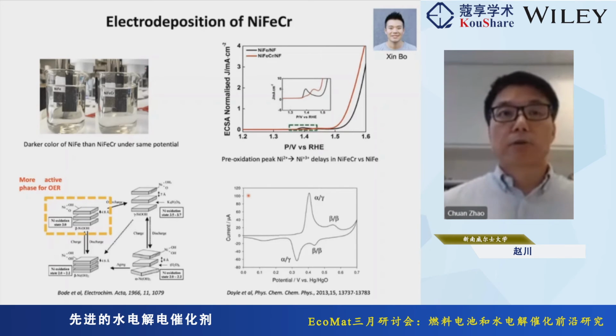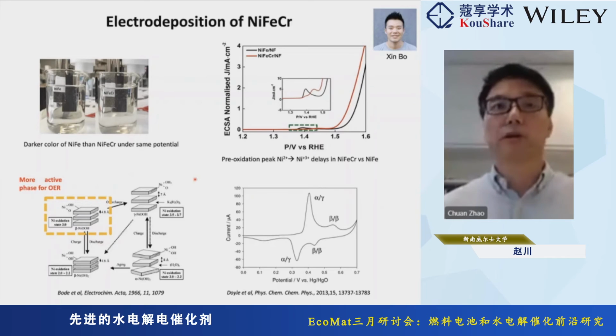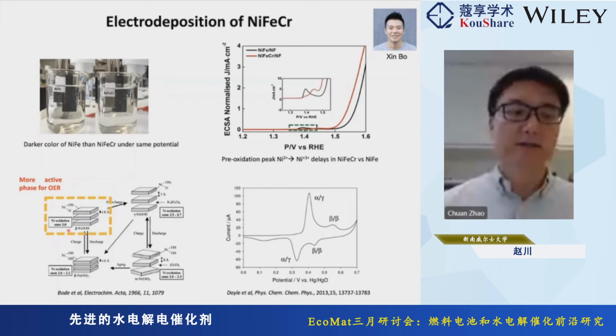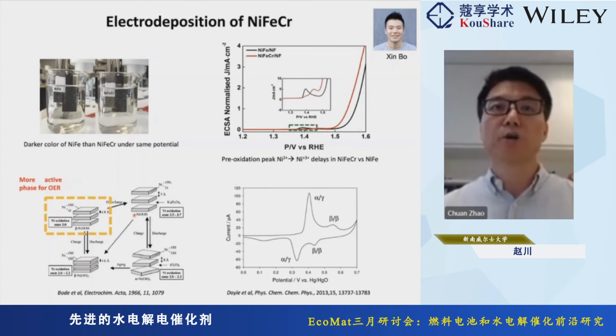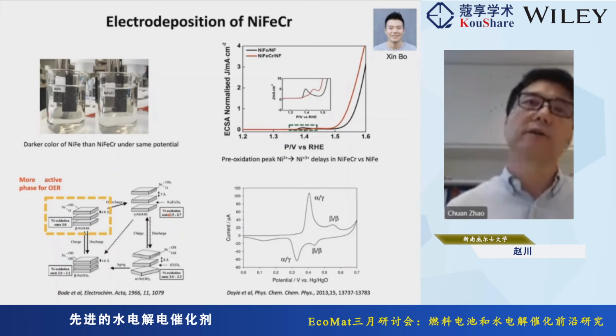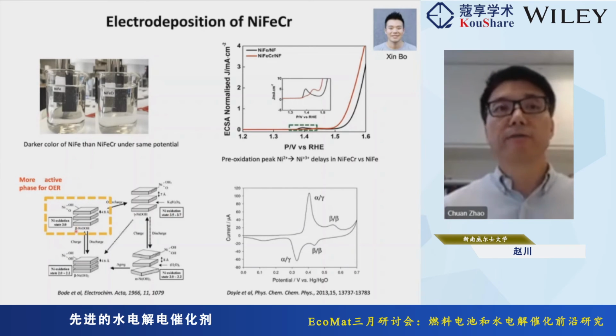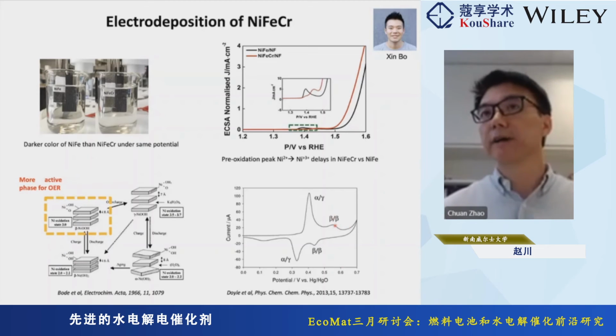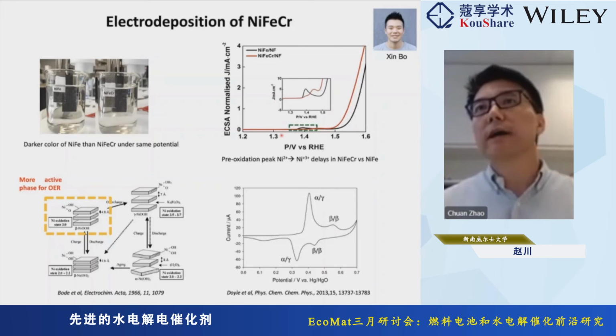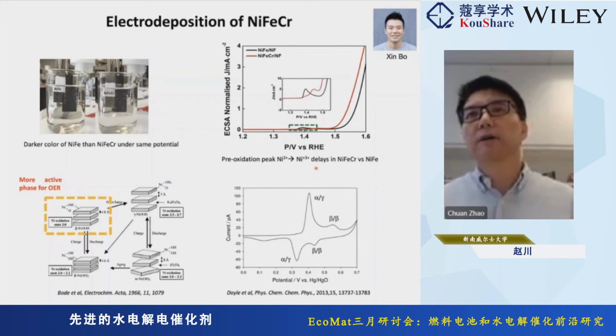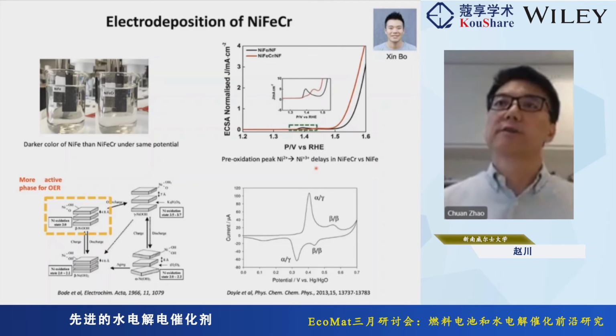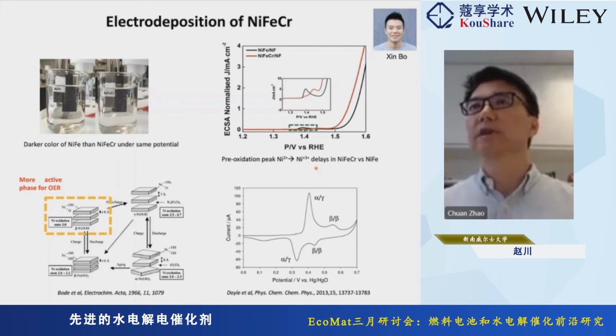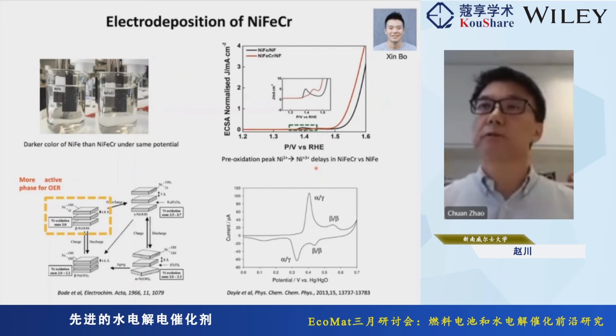So we know there are 4 active phases of nickel hydroxide responsible for OER, and usually the beta phase nickel oxyhydroxide is the more active phase for OER, where nickel has a relatively lower oxidation state. Well, the gamma phase has a much higher oxidation state, and the gamma phase nickel oxyhydroxide is usually formed at higher potentials. So from the pre-peak shift, we can have an immediate impression that we are forming beta phase nickel oxyhydroxide with a lower oxidation state for the nickel.